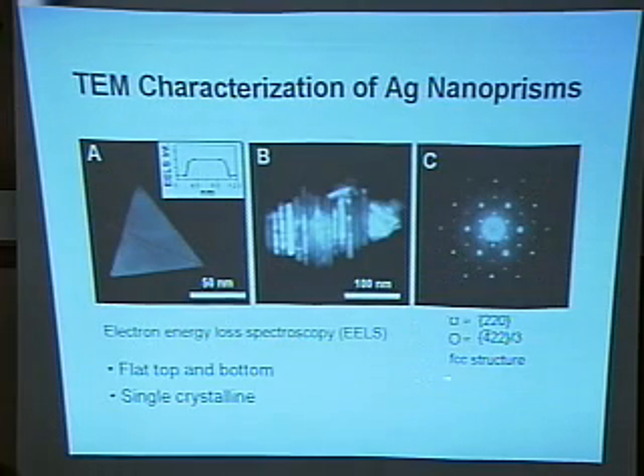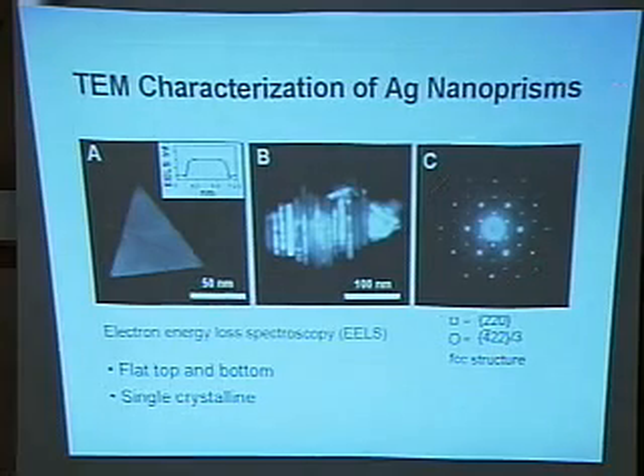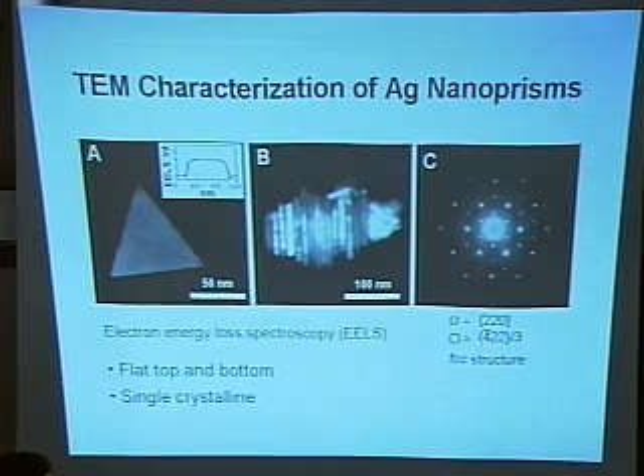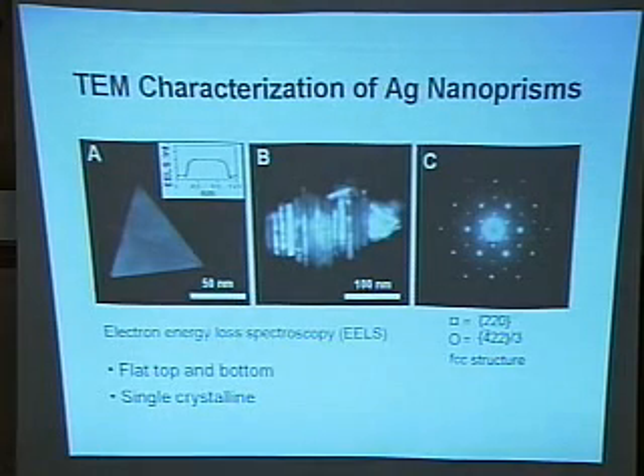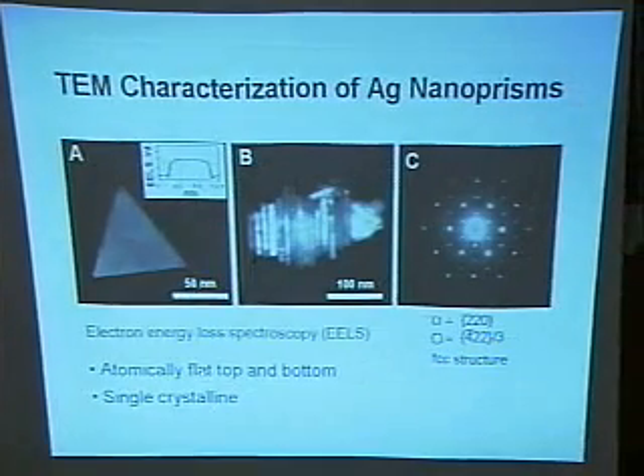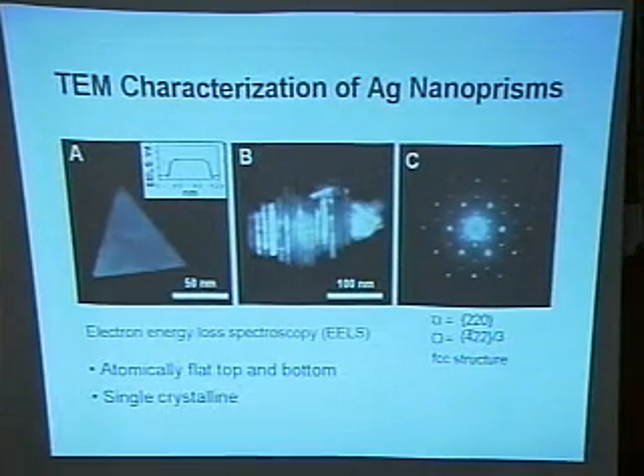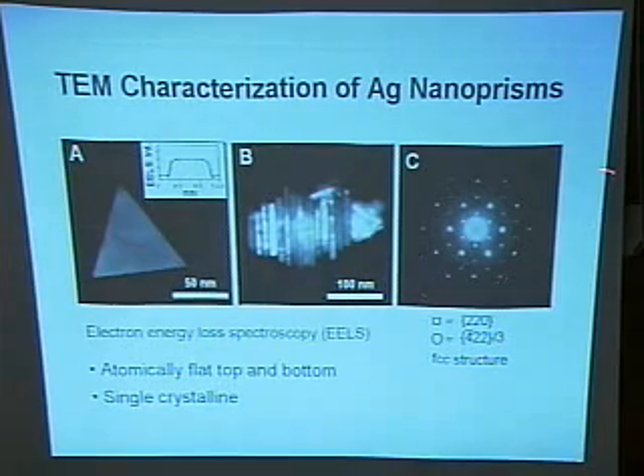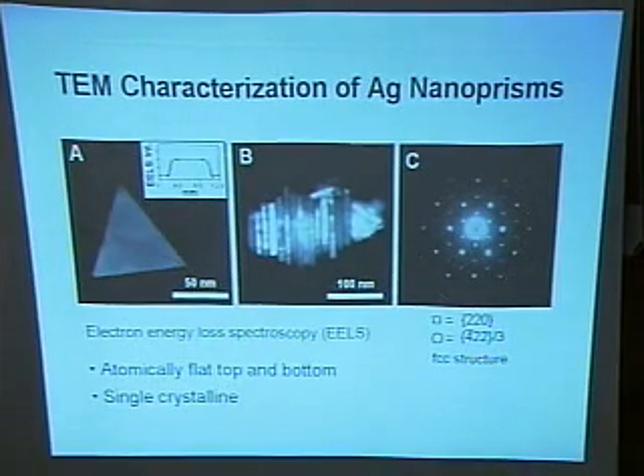They have FCC structures. If you take a careful look at this electron diffraction pattern, you will find it has an additional spot, which is the one-third 422 reflection. Which means the triangular particles have atomically flat top and bottom surfaces. This is a typical phenomenon from thin prisms, having additional electron diffraction dots beside the regular FCC structure.